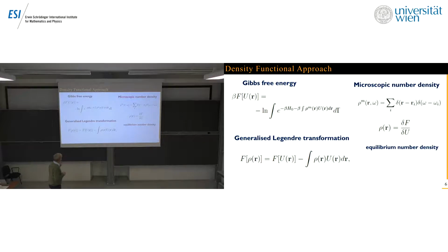That's the general way we proceed from the free energy as a function of external field, which we can, in principle, measure or calculate using the Gibbs free energy, to the free energy which depends on the density, and we cannot directly control density inside the materials. That's the problem. There is no general formula for this free energy, so it has to be derived somehow using approximations.